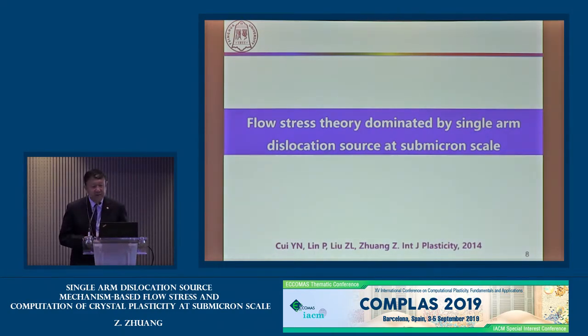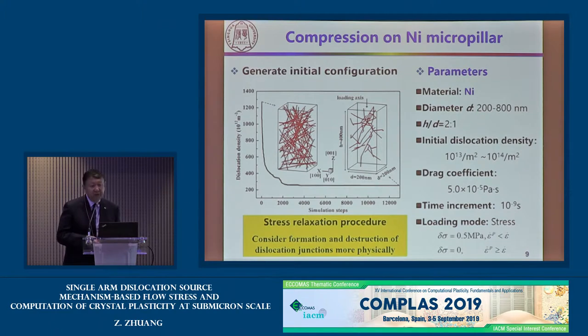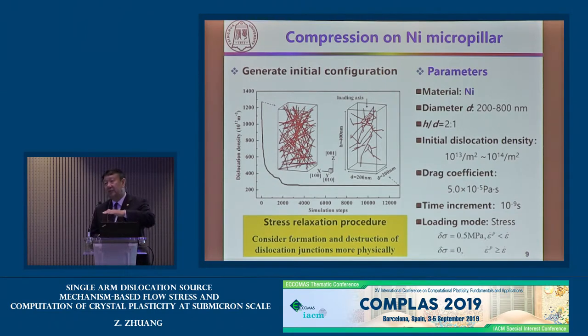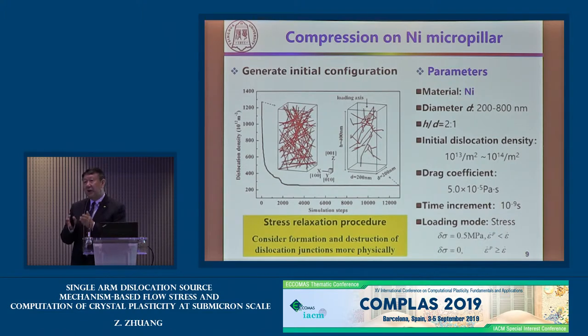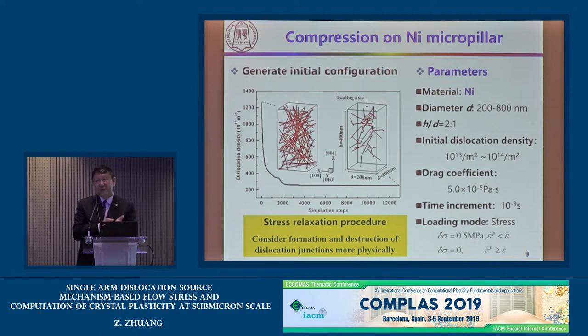First, we set up the flow stress theory dominated by single-arm dislocations at the sub-micron scale. We think about how to compress a nanopillar. We place the initial dislocation density configuration in the pillar, then apply compression. Because the surface is free, most dislocations can escape from the free surface — dislocation starvation. We can observe the dislocation density curve being reduced during compression, with most dislocations moving to free boundaries. From this, we can simulate and evaluate dislocation nucleation, evolution, and starvation in the pillars.